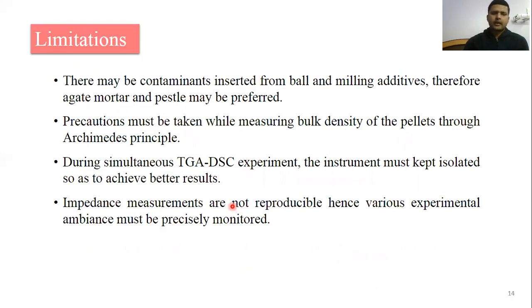Some of the limitations are that to avoid contamination from ball milling additives, we use mortar and pestle for grinding. Precautions have been taken to measure the density using Archimedes principle. During simultaneous TG-DSC analysis, the instrument must be kept isolated to achieve better results. Also, the impedance measurements are not reproducible, hence various experimental atmospheres must be precisely monitored.